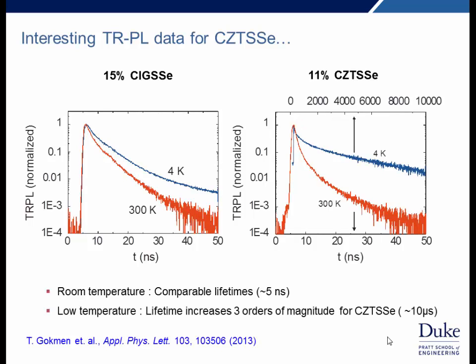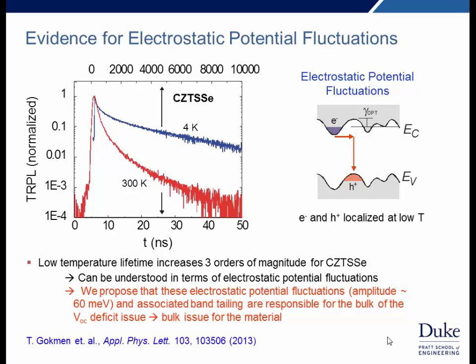But if we cool down, fairly dramatic things happen. CIGS is roughly the same, the lifetimes don't change. But for CZTS, we get around 3 orders of magnitude in enhancement of the lifetime. And this we take as evidence, or is indicative, of electrostatic potential fluctuations.